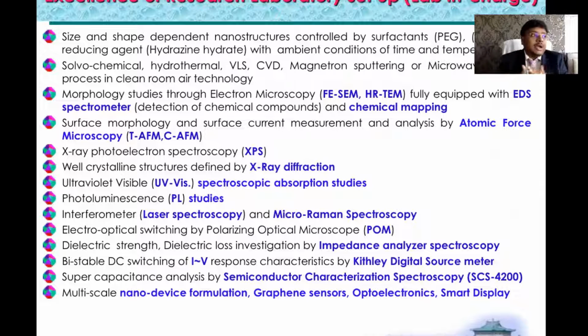And sometimes when you are approaching some chemical experiments, the nanomorphology is not growing very smoothly, sometimes there is obstruction, and some cluster particles will be there during the reaction time. So those kinds of surfactants will help for the smooth growth of whatever morphology you are looking for, let's say rod, sphere, particle, or hollow sphere, whatever, so that we can easily perform.